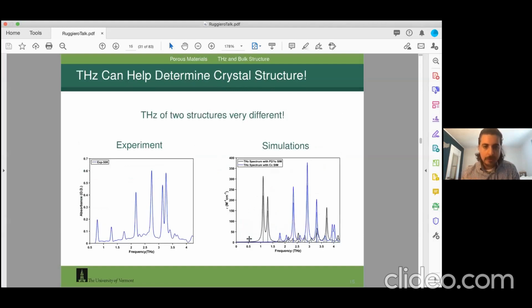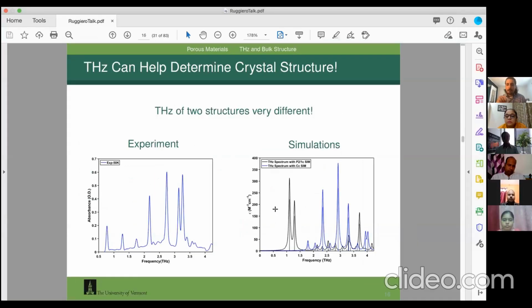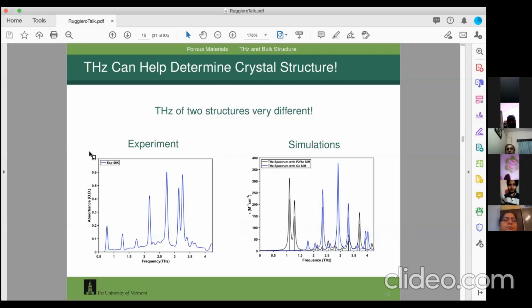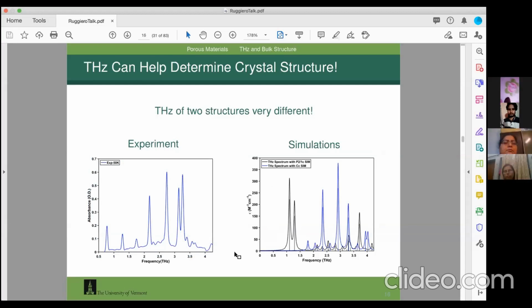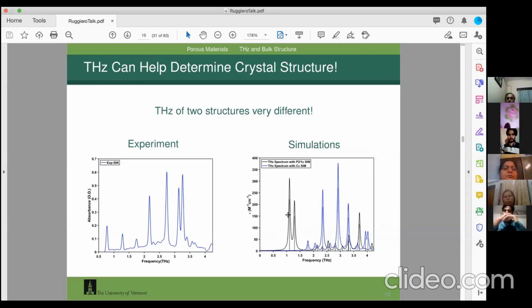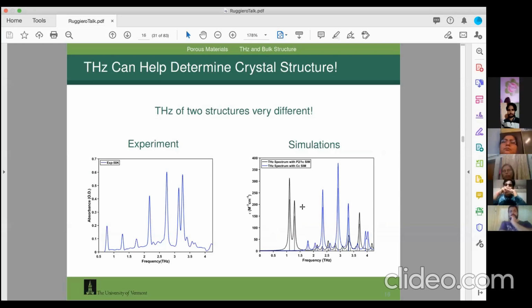However, if we simulate - so this is the experiment on the right. We took this in my lab at 50 Kelvin, and it matches the powder X-ray pattern, the experiment. But if we simulate the frequencies using the two different space groups, we get two very different terahertz results.